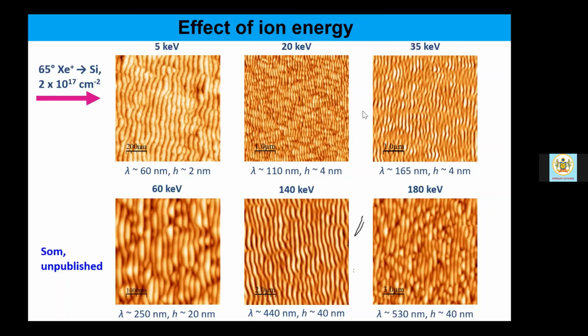The difference from left to right on the top frame is the increasing ion energy from 5 keV to 20 keV to 35 keV to 60 keV to 140 keV to 180 keV. So 36-fold enhancement in energy took place, that led to nearly an order of magnitude enhancement in the ripple wavelength. Lambda is the wavelength and h is the amplitude of the ripple pattern. So amplitude also enhanced by nearly 20 times.